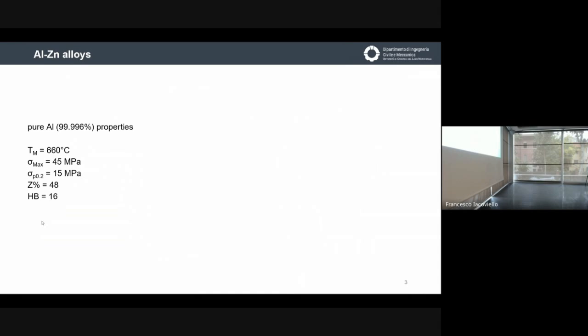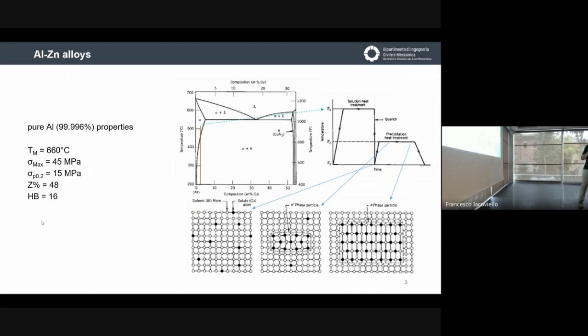You can see that the resistance of aluminum is ridiculous. It's no good. You have to do something to improve this. And the solution is to generate something in the structure able to block the movement of the dislocations. The first technique is to use an addition of other components, for example copper, and use the property of the limit of solution to create the zone where the dislocation is blocked.